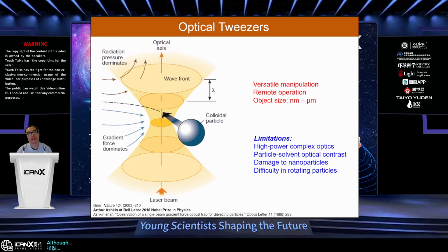Although many breakthroughs have been enabled by traditional optical tweezers, there are some limitations which prevent their further applications, including just a few examples. Because the working mechanism relies on optical forces, which are very weak, a high power laser beam is usually needed to manipulate and trap the particles. Also, since it's a basic optical phenomenon, it requires a good contrast for the objects we are going to trap. For example, take this colloidal particle, which is typically in a solvent. It requires a good optical contrast, which means the refractive index of the particle to be trapped by the laser beam and that of the solvent should have some difference.